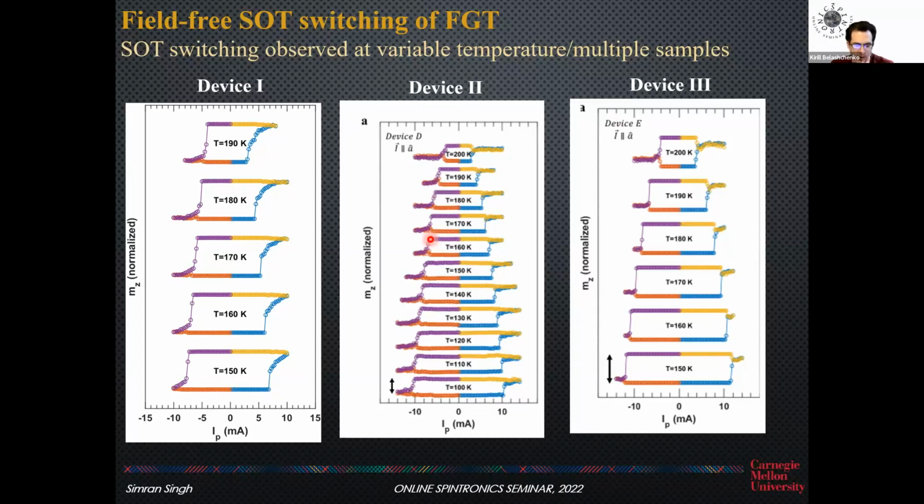It would be nice to know that it scales with the thickness of FGT, like you expect the spin-orbit torque to scale. So you're thinking we keep the same thickness of WTe2 and change the thickness of FGT? The thickness of the TMD probably doesn't matter in terms of the generation of spin current, but the anisotropy could be different, and the pinning field can be different.